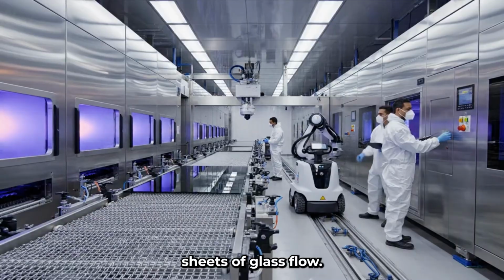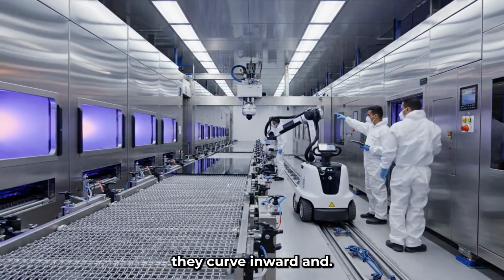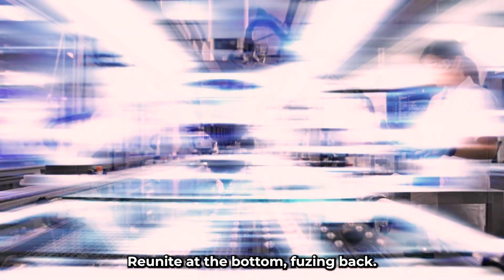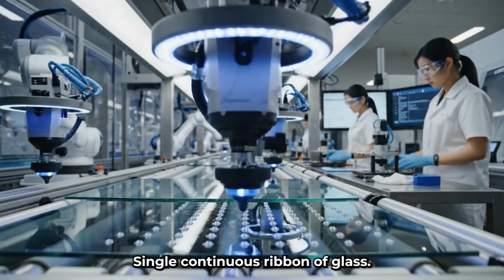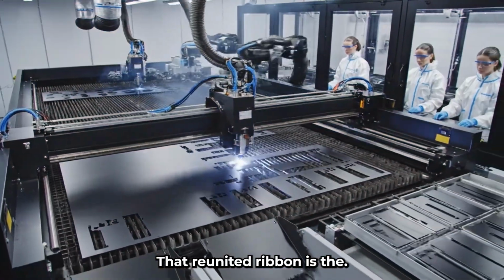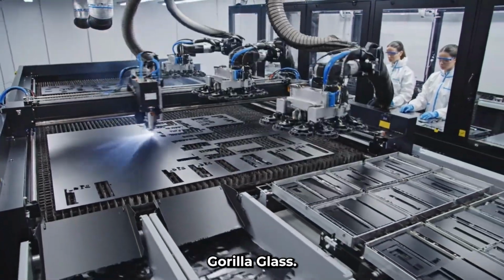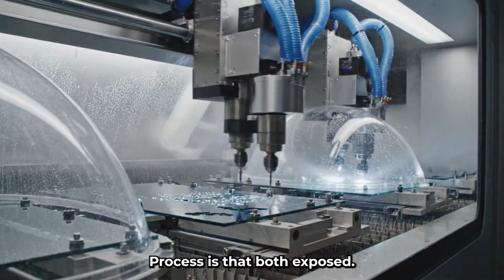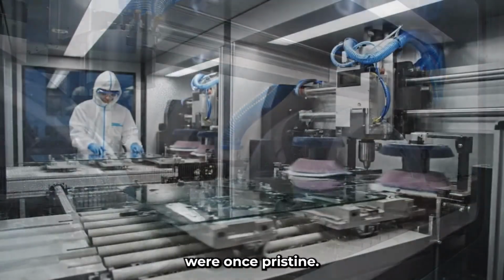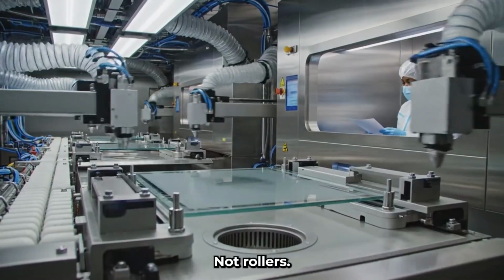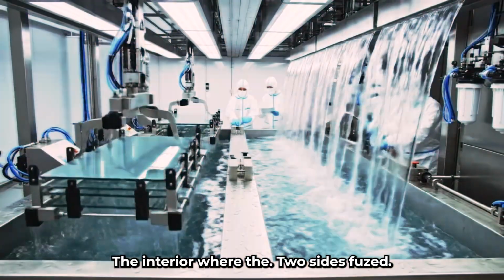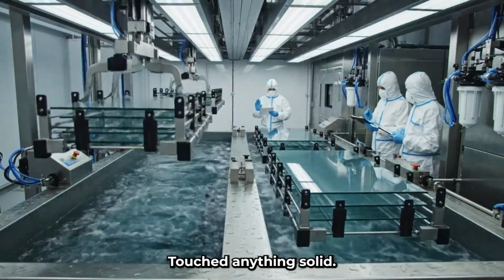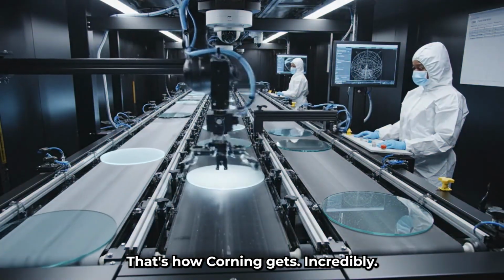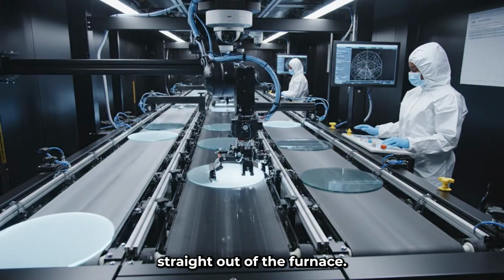As those two glowing sheets of glass flow downward under gravity, they curve inward and reunite at the bottom, fusing back together into a single continuous ribbon of glass. That reunited ribbon is the sheet that will eventually become Gorilla Glass. The genius of the process is that both exposed surfaces of that sheet were once pristine, untouched liquid surfaces that only ever met air. Not rollers, not molds, not metal. The interior where the two sides fused is protected, and the outer surfaces never touched anything solid. That's how Corning gets incredibly smooth, flaw-free surfaces straight out of the furnace.